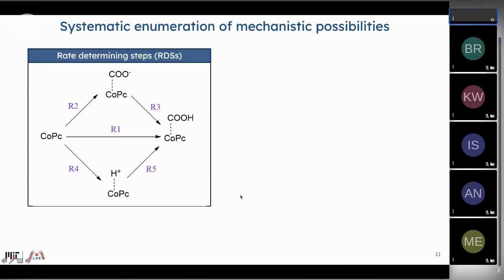So we decided to systematically enumerate the different mechanistic possibilities. First, I've sketched out here a direct step R1, which is a proton-coupled electron transfer to CO2 to get from CoPc to this intermediate. There's a branch where there is first an electron transfer and then a proton transfer, and then another branch where there is a proton transfer and then an electron transfer. For us this was what we refer to as a square scheme, in which all the different mechanistic possibilities for that single step we're interested in have been laid out.